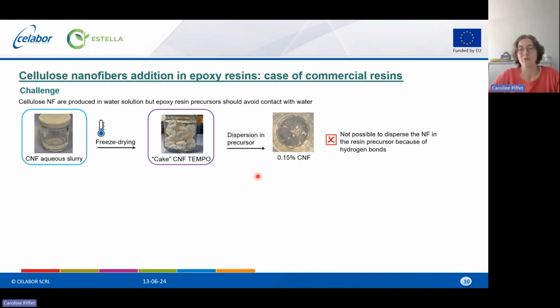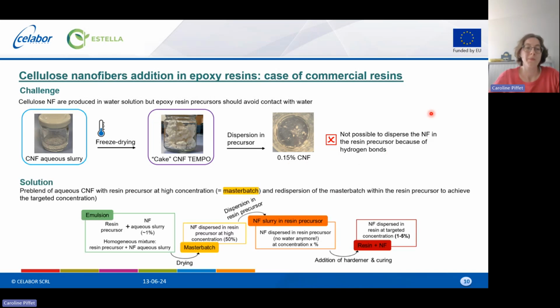But the problem is that when you dry the cellulose nanofibers, it is very, very difficult to disperse those nanofibers again, because the hydrogen bonds between the cellulose chains are very strong, and you obtain only pieces of nanofibers not properly dispersed, even at very low concentration. So we decided to develop a new strategy, and this strategy consists in pre-blending the aqueous nanofibers with the resin precursor at a high concentration.